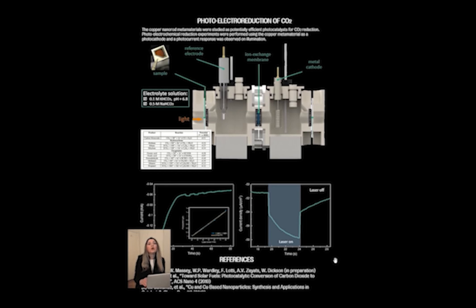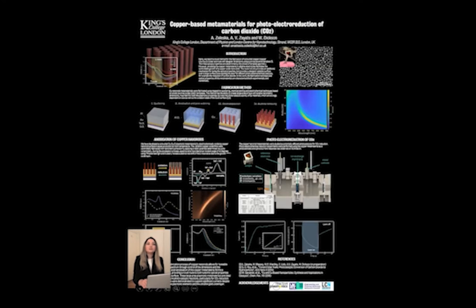As expected for a hot carrier-driven process, the plasmonic photocathode copper nanorods exhibit a linear photocurrent response with respect to incident light power. Next step is now to quantify and qualify resulting products via NMR and study catalyst selectivity. To summarize, this presents a great opportunity for driving photoelectrochemical reactions, such as carbon dioxide reduction reaction at the nanoscale, using hot carriers from plasmonic metal nanostructures.